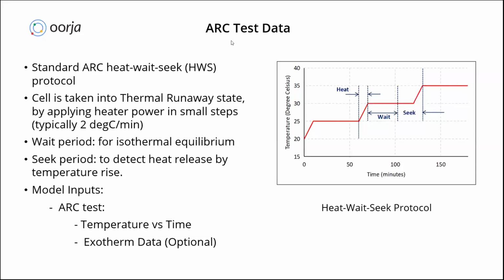For that, the ARC data that we use is a standard heat wait seek protocol. As many of you must be familiar with this ARC protocol, the cell is forcibly taken into thermal runaway state by applying small heater power in small steps, which is typically taken as 2 degrees Celsius per minute. After the heat is applied, there will be a certain wait period in order to let the cell reach isothermal equilibrium. After that, the seek period is given, wherein it will detect the heat released by the temperature rise itself. So with this heat wait seek protocol, it will check how the cell is getting into thermal runaway.